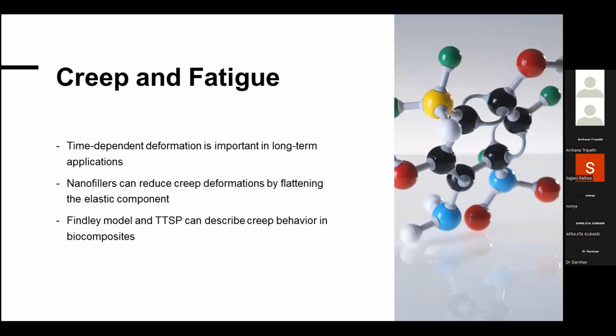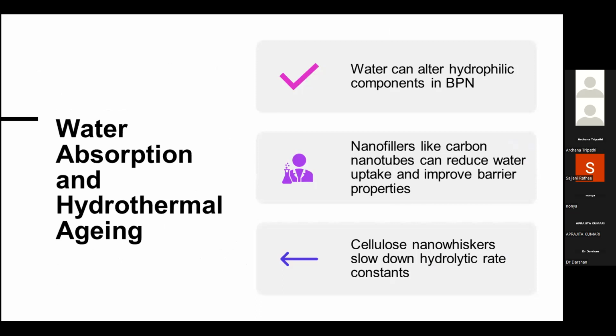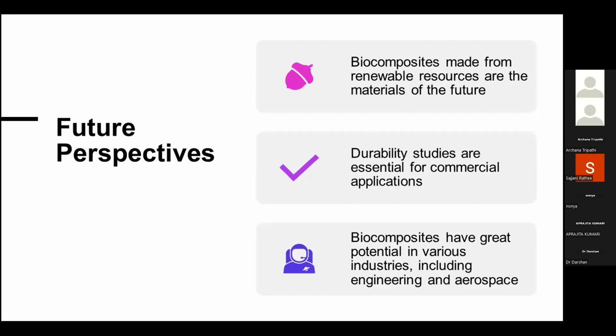Creep and fatigue. Time-dependent deformation is important in long-term application. Nanofiller reduces creep deformation by flattening the elastic components. Findley models and TTSP can describe creep behavior in biocomposites. Water absorption and hydrothermal aging. Water can alter hydrophilic components in BPN. Nanofiller like carbon nanotube can reduce the water uptake and improve barrier properties. Cellulose nanowhiskers slow down the hydrolytic rate constants.